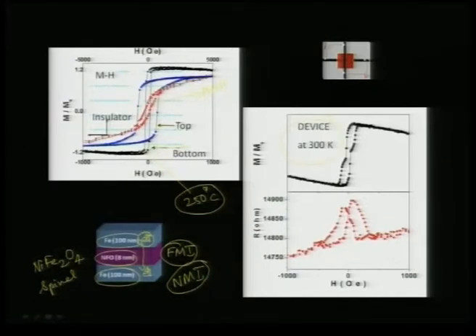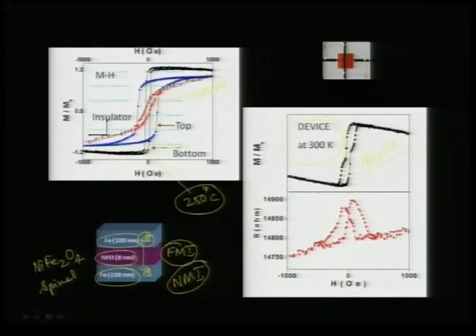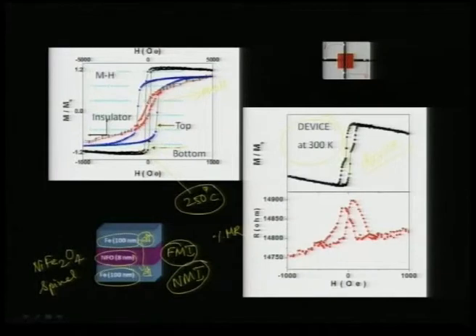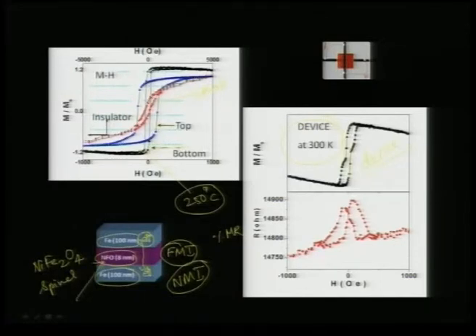What is unique about this: you have a staircase-type hysteresis loop, which is typical for a device. If the device is performing, you have the staircase feature, and then the magnetoresistance also shows a pronounced activity. Although the order of percentage MR is rather low, you can clearly see this butterfly-wing-shaped MR curve, which clearly shows that this sort of magnetoresistive feature can be accomplished with a ferromagnetic insulator.